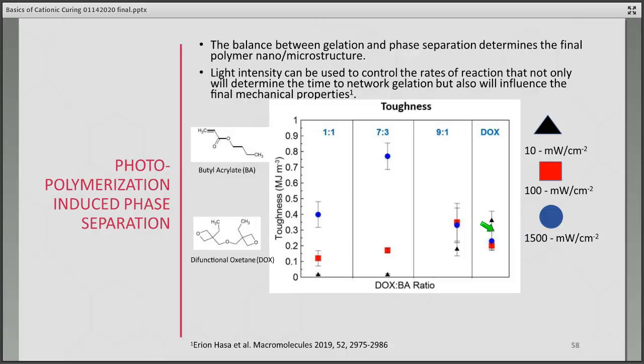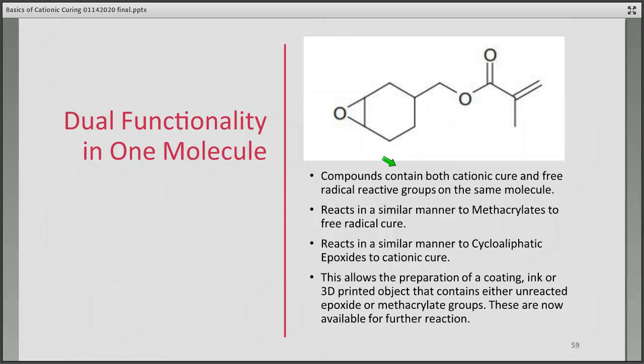The properties of the oxetane, or DOX, in toughness can be found here, somewhere between 0.2 and 0.4. However, when he combined that in a hybrid system, with a DOX to BA ratio of 7:3, and exposed it to different levels of light, here we see a dramatic increase in the toughness of the system. At the lowest level of light, there's barely any reaction. Something comparable at 100 milliwatts. However, at 1500, you got a dramatic increase in toughness. So just by using the light intensity, you're able to modify properties.